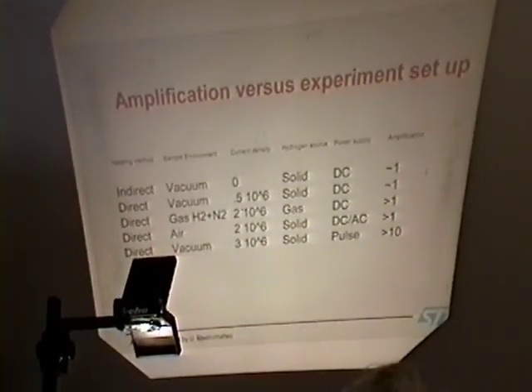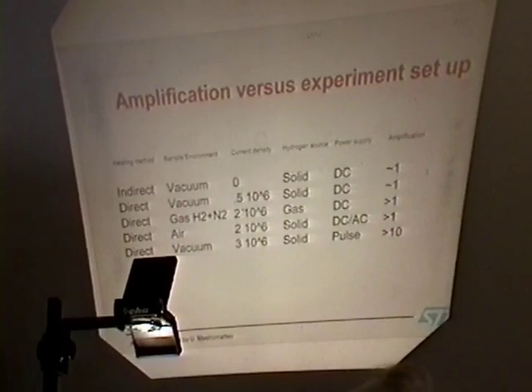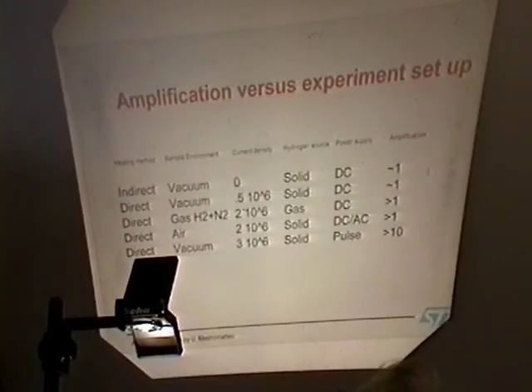You mentioned a threshold for current density at these lower loadings. Could you comment on that? What is the threshold and how does it vary, say, with temperature and so on? Yeah. On all the experiments I did, I saw a big difference in the speed of the reaction using different conditions and different current densities. I can see that approaching 10 to 6 amperes per square centimeter, we can get quite high reaction rate.